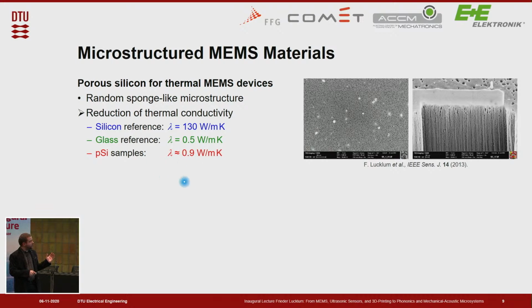And you can see also that the porosity, so the amount of holes versus remaining solid volume, is not very high. But even though it's only about 50% porosity, we can reduce the thermal conductivity by orders of magnitude, way more than you would expect if you would think about it just as a mixture of materials. And we'll come back to this. This is the takeaway from this project. Microstructuring a material allows you to change the physical properties way away from the naturally occurring physical properties.